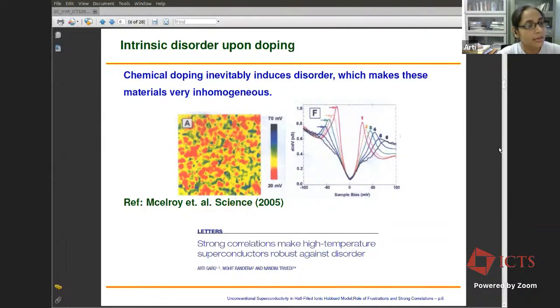And this is very easily reflected in these STS experiments on high TC cuprates, which provide the local density of states map for these materials. And you can see that the superconducting gap has inhomogeneity on the nanoscale. As you move from one point to another, you see that the superconducting gap changes a lot. So it's very important to come up with theoretical and experimental solutions where one can have high TC superconductors without doping. And my talk today is something along that line.